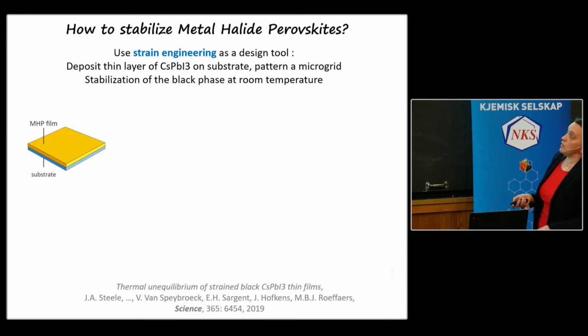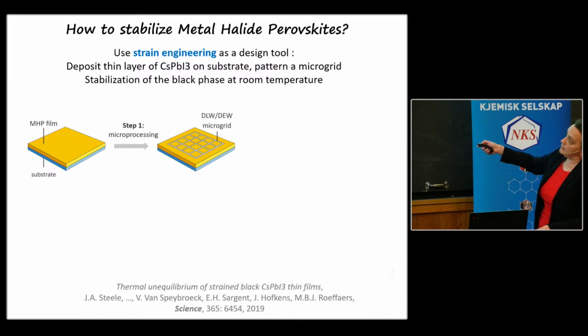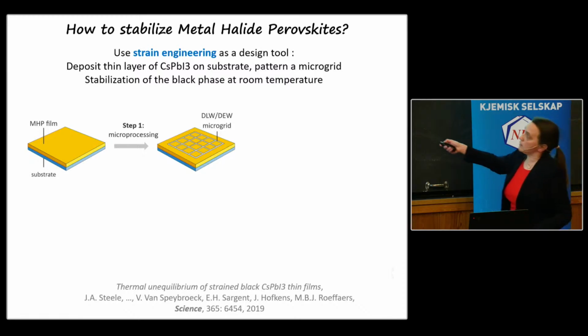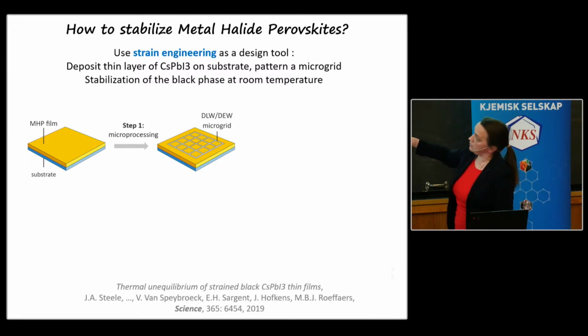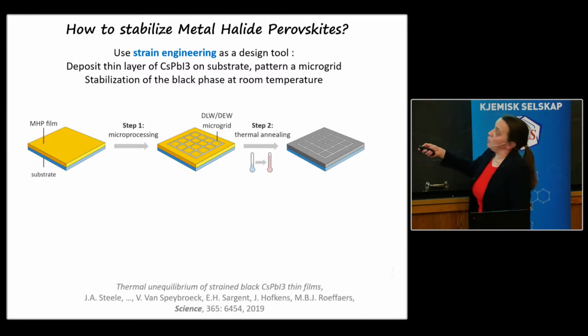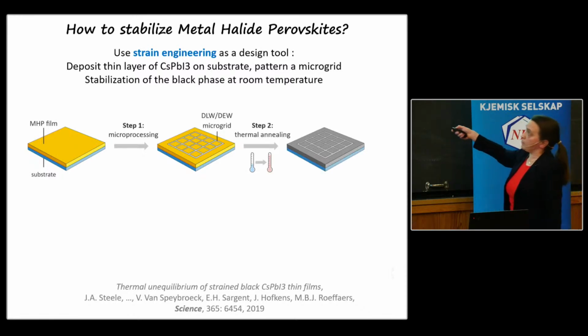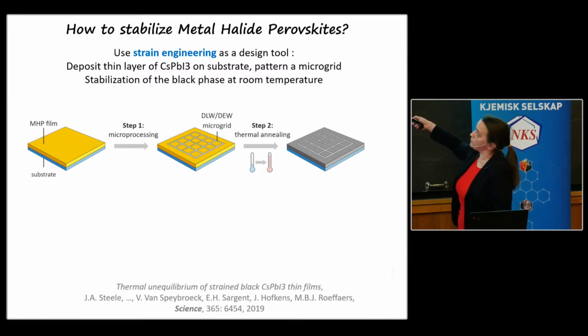So what the experimental colleagues did is they found a strategy. They deposited it as a thin film on an underlying substrate. Then they made some patterns, a micro-patterning here. So here you start from the thermodynamically stable phase, the yellow phase. That's the reason why it's yellow. We make a micro-pattern into this thin film. Then we increase the temperature to bring the material into the optically active phase. That is what you can see here.